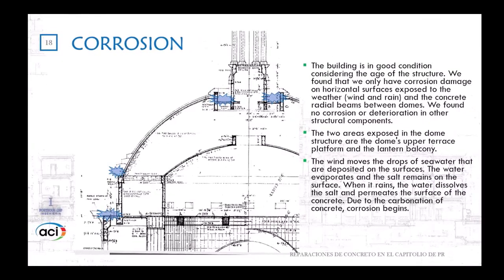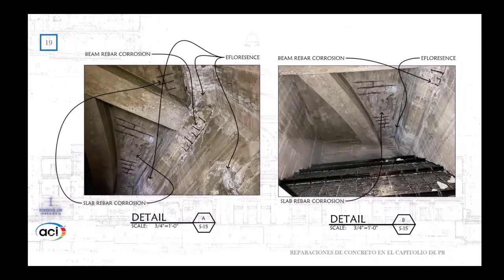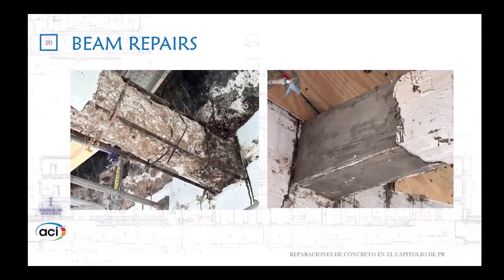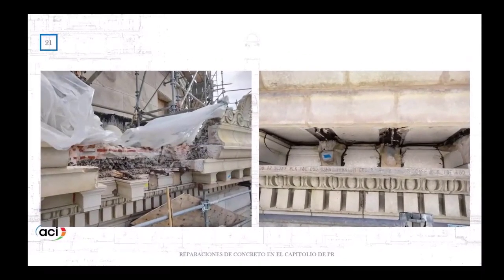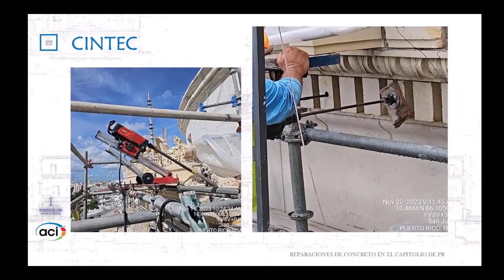The basis of corrosion was the horizontal surfaces between the dome construction, where salt water, like Pablo said, deposits. Every time it rains, the salt water goes inside the structure, and that's why they were using regular techniques. It's very important to detail the drawings. Here are photos of the damaged beam, the repaired beam, and then the terracottas, where the damage was much larger. This shows you the process of the CINTEC.